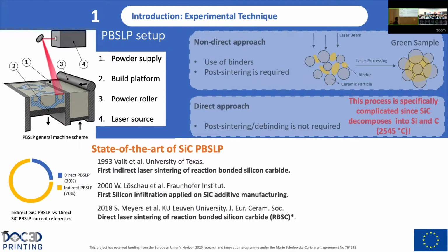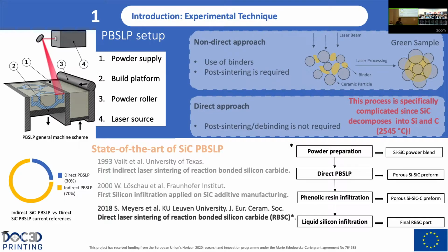we can see that 70% of the references are related to a non-direct method and 30% to direct methods. And if we look at the latest strategies followed by authors, researchers, and industry, for the additive manufacturing with powder bed selective laser processing of silicon carbide, initially they used a silicon and silicon carbide powder mixture. After the additive manufacturing process, they obtained a silicon carbide preform. After, by performing polymer infiltration pyrolysis of a phenolic resin, which is a precursor of carbon, they obtain a silicon carbide carbon preform. And finally, by carrying out liquid silicon infiltration, they obtain a final reaction-bonded silicon carbide.